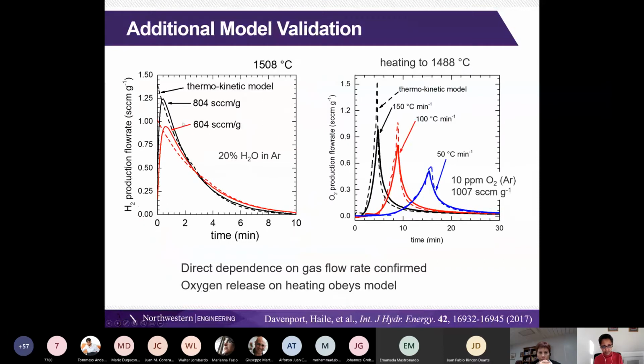Okay, so other aspects of validating this model: I told you that the oxygen release or the hydrogen production should be dependent on the gas flow rate. And here we change the gas flow rate, and you can see the apparent kinetics change. We've done this also by simply changing the amount of material, and this is normalized to the grams of oxide in the material. So it's not simply that we're having a proportional change in the amount of hydrogen. Even after we normalize for the grams of oxide there is a difference, because the thermodynamic driving force is influenced by how much material we have in the reactor. So we see all of that.